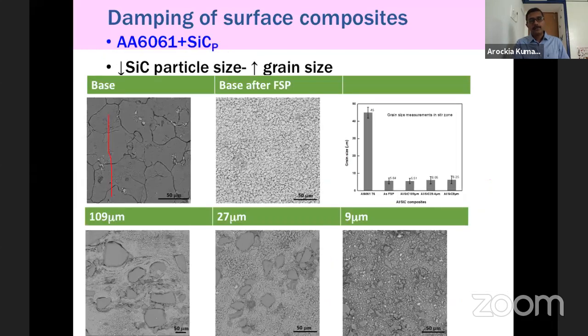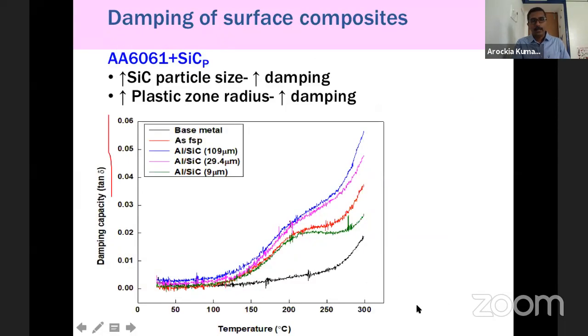Similarly, we have incorporated silicon carbide particles. What we are seeing here is that we have incorporated 3 different sizes of silicon carbide particle, and we have studied the influence of particle size on determining the damping. We found that by incorporating very large size particles, that's what you are seeing in this blue color, we are able to increase the damping more effectively.